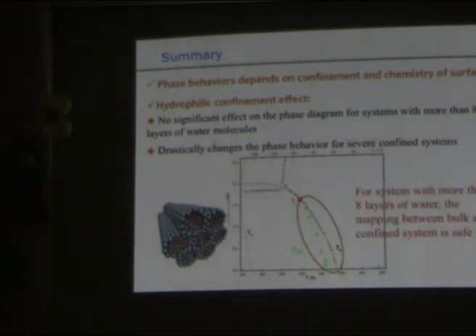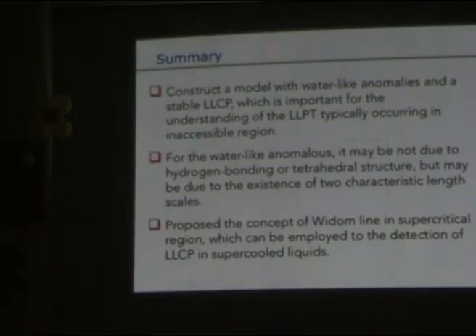If we go back to the experimental data, this circle was the bulk data, and this is the confinement data. This has a requirement. If you want to apply your confinement data on top of this bulk data, it requires your dimension, for instance if you are in a nanopore, to be more than 8 layers, at least according to all studies. Okay, so this puts a lot of constraint on the interpretation of the experimental data. I will probably stop here and give a really brief summary of all of that.